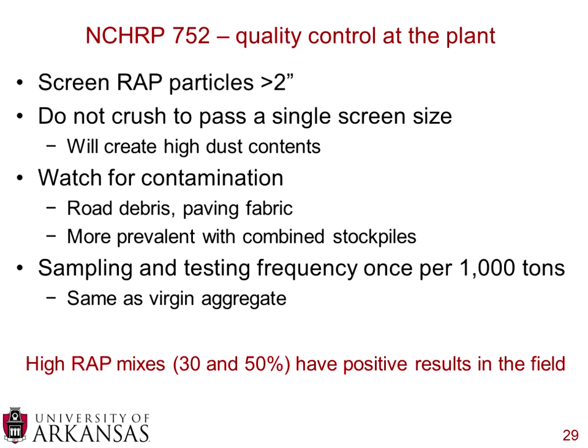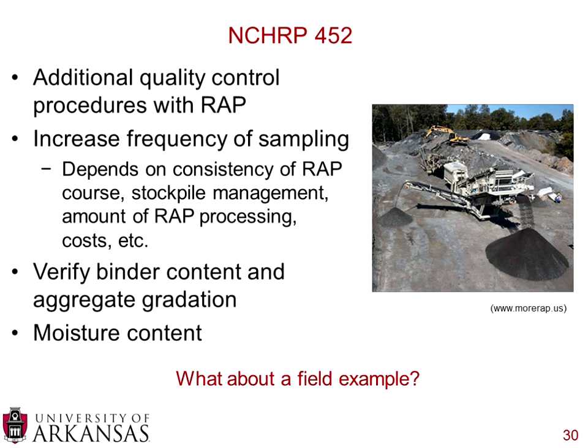And you also certainly want to watch out for contamination in combined stockpiles, because if you have several different stockpiles, you just increase the chances of something foreign getting into there that you don't want in your processed RAP pile. And they recommend in NCHRP 752 that you sample and test at the same frequency as virgin aggregates, which is once per every 1,000 tons of material used. Now, I do want to say that NCHRP 752 did some review of field sites, and they found that high RAP mixes using either 30 or 50% RAP in a mixture did have positive test results in the field, but they didn't go into a whole lot of detail about that. It was more of just an identification and survey of that.